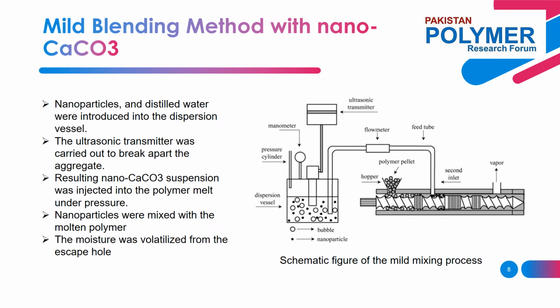In another research, a novel approach of preparing polymer and nano calcium carbonate composite was presented. A certain amount of nano calcium carbonate particles and ethanol were introduced into the dispersion vessel, and particles were wetted sufficiently by mixing for 10 minutes. Deionized water was added in the vessel, and an ultrasonic transmitter was used to break apart the aggregate structure of nano calcium carbonate and uniformly disperse the nanoparticles into the suspension.